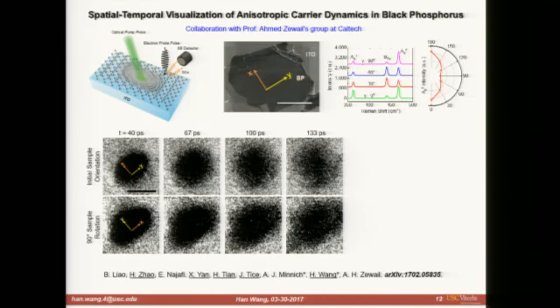The laser strikes, it generates free carriers, and the carriers diffuse in all different directions. These are hot carriers. As time goes by, you can see the carrier diffuses much faster along the X direction of the crystal and a lot slower along the Y. So this spot expands more along the X direction and much less along the Y direction. These circles are just to guide your eyes.